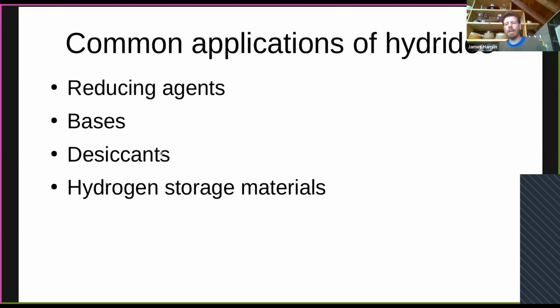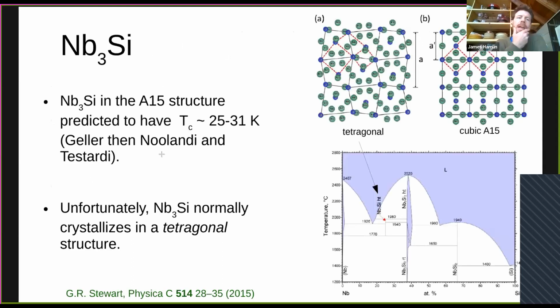So one example that we have been interested in is niobium-3 silicon. I want to bring this up merely as an example of what a metastable material really is, what we really mean by metastable. Niobium-3 silicon in the A15 structure is predicted to have a TC of 25 to 31 Kelvin. Unfortunately, it doesn't actually crystallize in this A15 structure. It instead crystallizes in a tetragonal structure. And in fact, even this tetragonal structure is metastable.